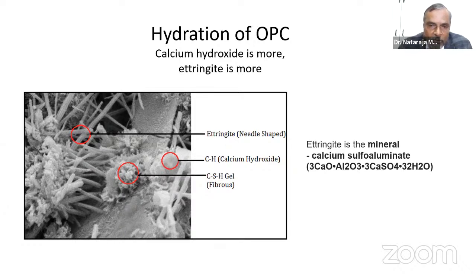But if you take slag, for example, ground granulated blast furnace slag, there are instances that researchers have used it to the extent of 75% and going up to 90% slag, maybe just 5% of clinker, and maybe another 3 to 4% of gypsum. They are getting super sulfated cement. So one of the best possible cements from the durability point of view. And in fact, this super sulfated cement is also recommended in IS 456, and that is where the application of high volume fraction of slag comes into picture.